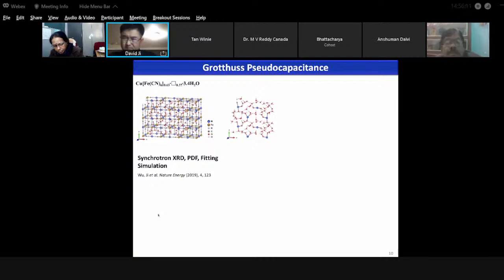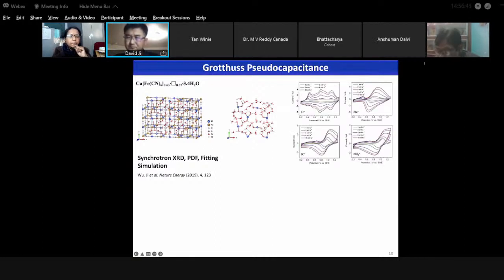When we remove parts of the nexus or the islands of the structure, we can actually have a lot of defects to host water molecules as lattice water molecules. And these lattice water molecules, if they're close enough and they start to talk by hydrogen bonding, they're going to have a hydrogen bonding network. And with that, we will have the Grotthuss mechanism, right? So that's the hypothesis.